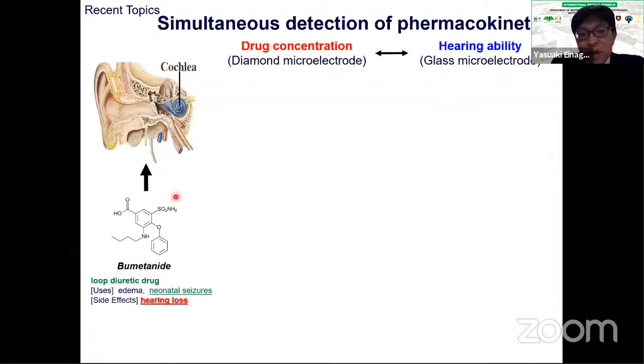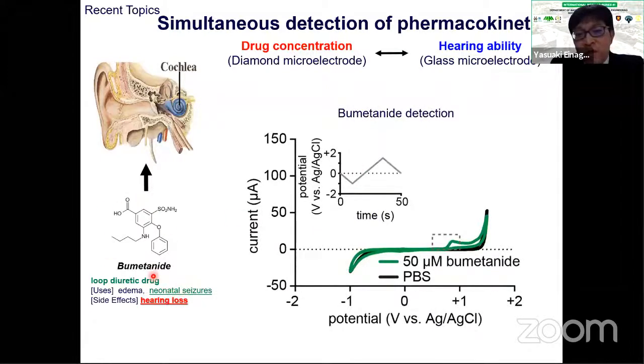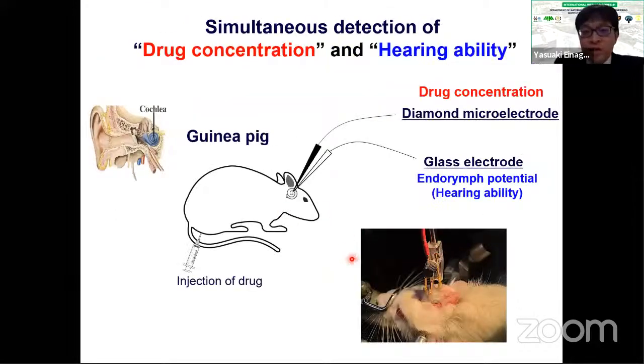Okay. So in the beginning, we checked the electrochemistry of bumetanide, this drug. As you can see, this is the oxidation of bumetanide, and it is very clear because it is observed by using diamond. Other electrodes are unable to detect it. So diamond is very nice. Then this is in vivo detection. We collaborate with a medical school, and this is our boron-doped diamond microelectrode, and this is a glass electrode. By this diamond electrode, the drug concentration is monitored, and by this glass electrode, the hearing ability is monitored by this endolymph potential. So we simultaneously monitor these signals, and then inject the drug.